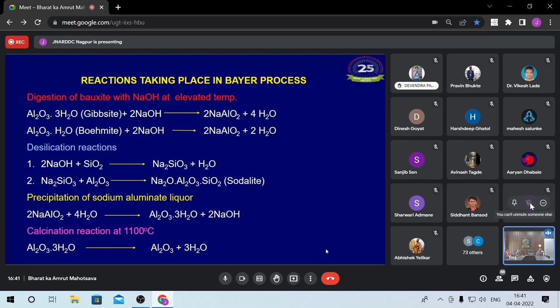Like Nalco company is going for a temperature of 107 degrees, that is called atmospheric pressure digestion, at a caustic concentration of around 220 GPL. Similarly, many people like Vedanta are operating at a caustic concentration of around 175-180 at a temperature of around 145 degrees. Those bauxites which contain boehmite require relatively higher temperature. In that circumstance, even if the caustic concentration is around 165-170, they have to go to a temperature of around 240 degrees to dissolve the boehmite, because boehmite requires a higher temperature.